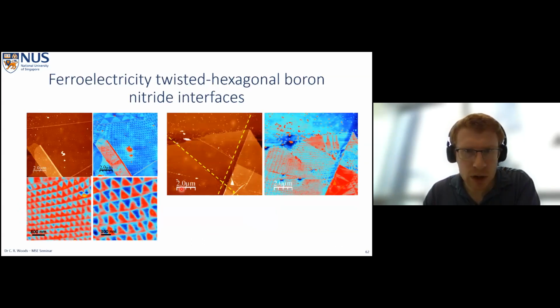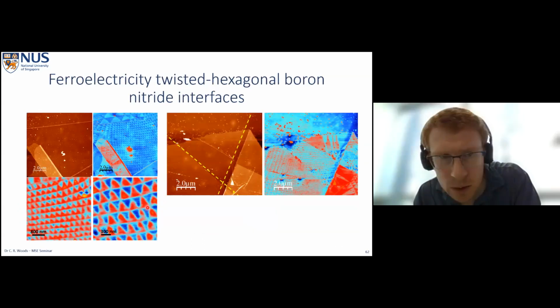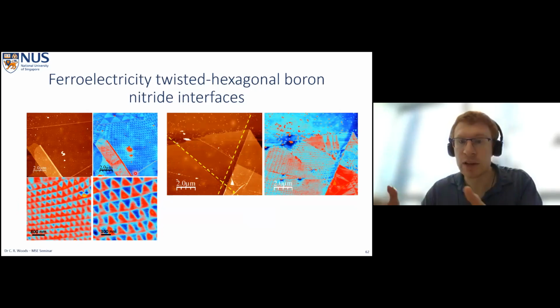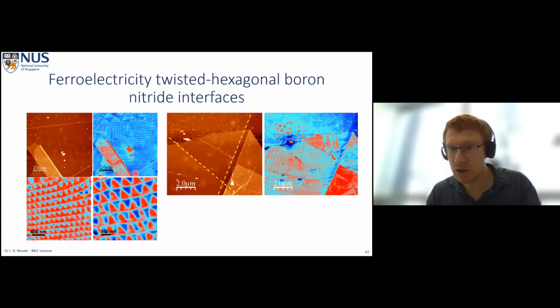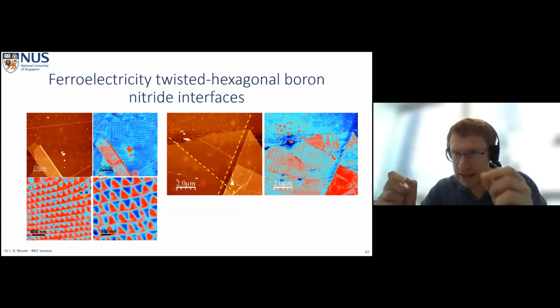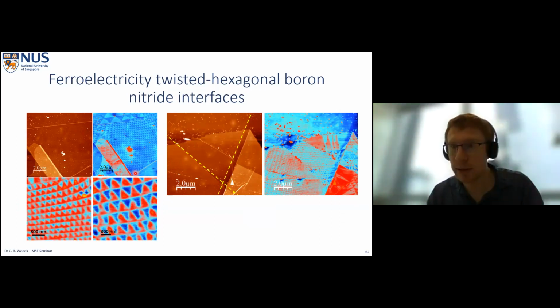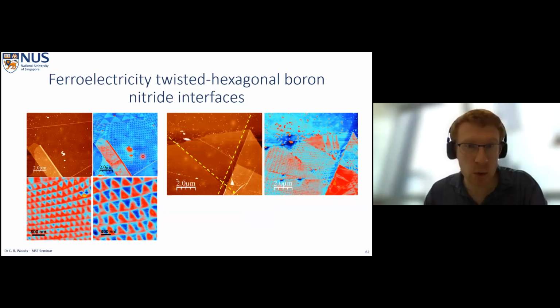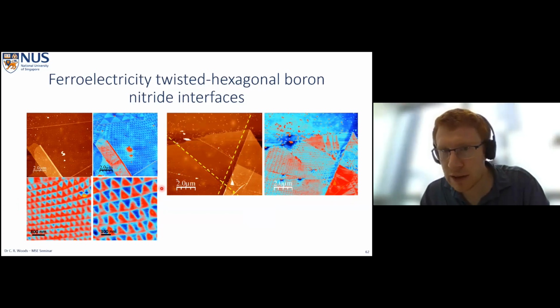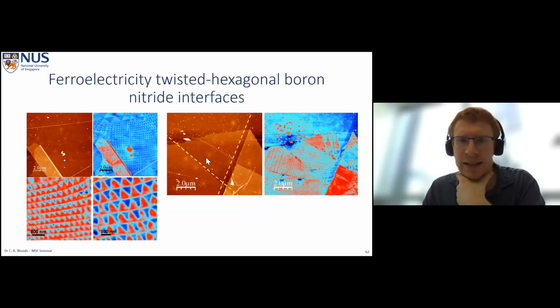I'm actually a bit surprised that I don't have one to show you. It would be interesting to show you because these bubbles have a strain distribution around them. So we would see that strain distribution in the superlattice as well, but I'm disappointed to say that I don't have something like that to show you. But in short, the contamination is not a problem for looking at this effect because of this self-cleaning mechanism, because of this ironing out of the interface. I hope that answers your question. Okay, thanks for the talk.